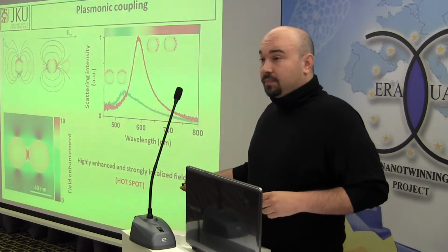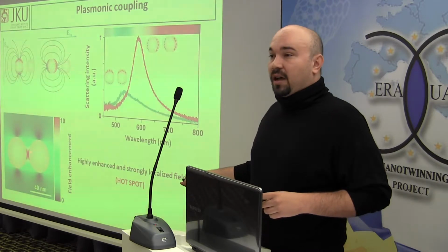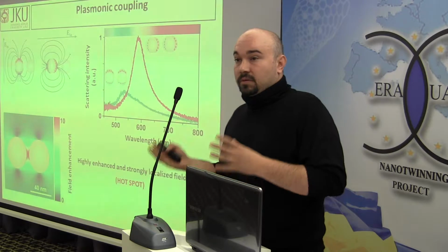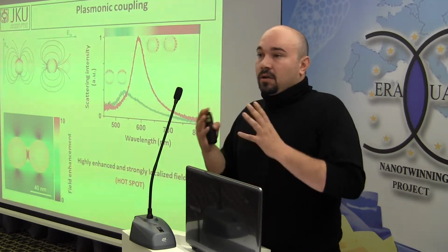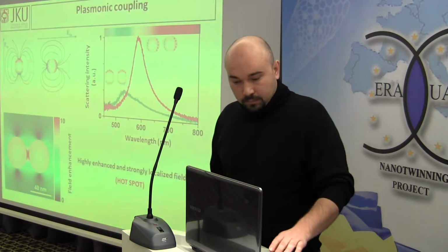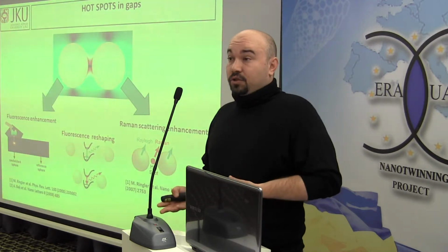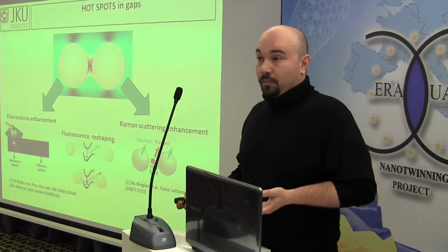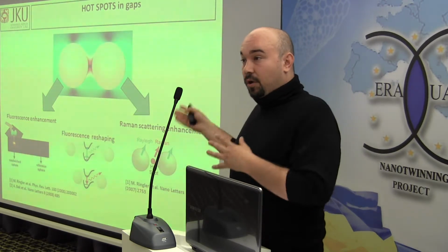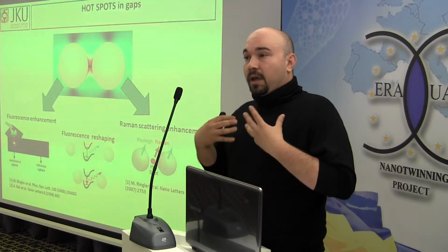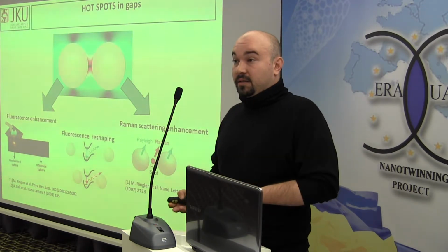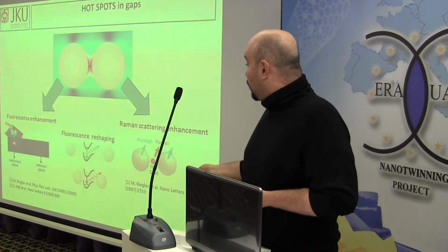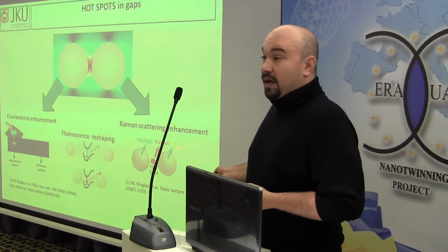And in the near field, the field is localized in the gap between the nanoparticles and highly enhanced. That's why, for historical reasons, one calls it a hotspot. Why are such hotspots interesting? First of all, they focus light in this nanoscale volume. So when we place a molecule inside this resonator, we have a high light intensity to excite the molecule. And in these terms, we can enhance fluorescence, or even reshape it, or enhance Raman scattering.